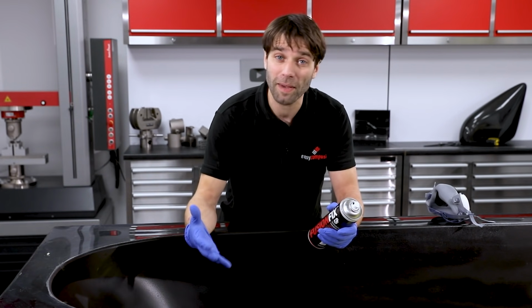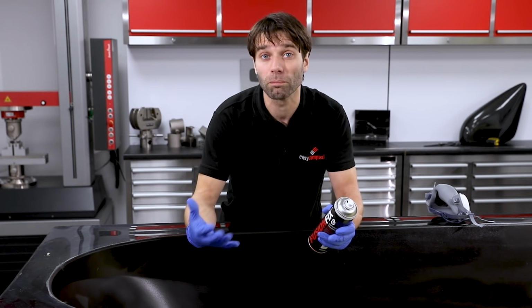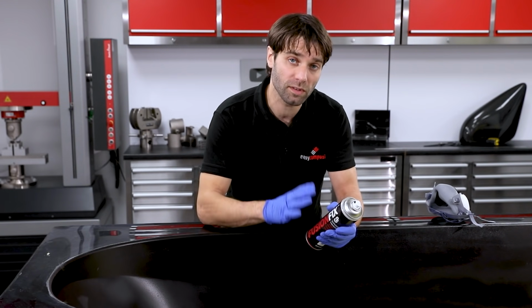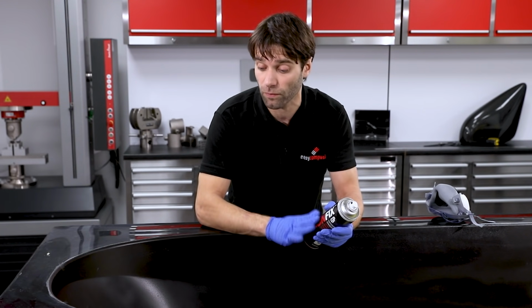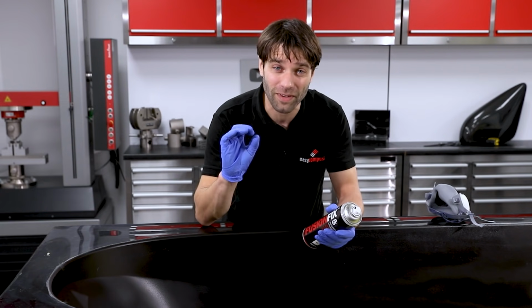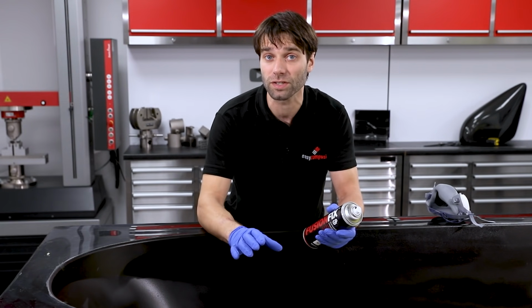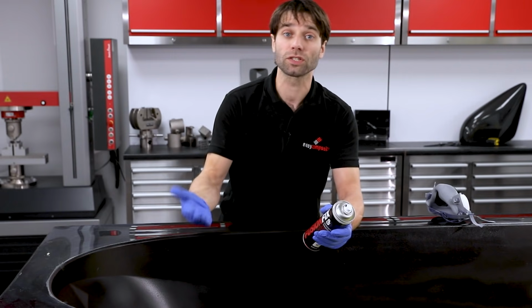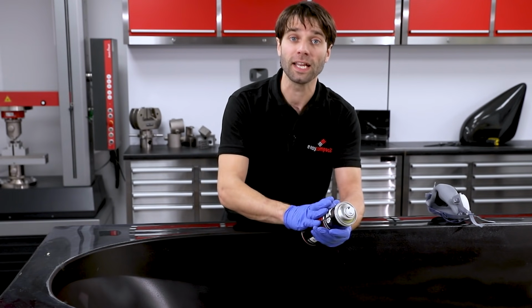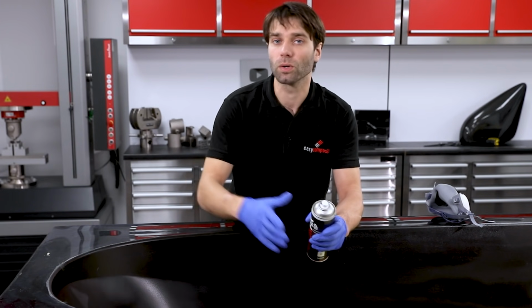If you were working on a cosmetic carbon part with a clear or even more likely no gel at all, I wouldn't advise using the Fusion Fix spray adhesive for that application because it can lead to very slight milkiness and imperfections on the surface. After the first ply, on the subsequent backing plies, you can use it as long as you're using it lightly and it won't cause you any problems.